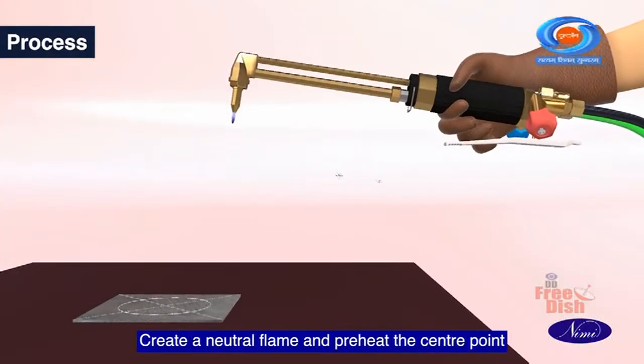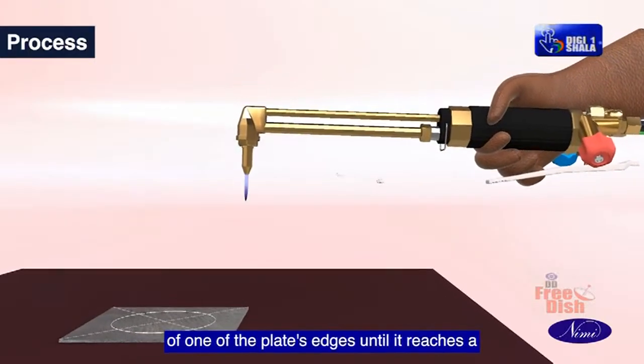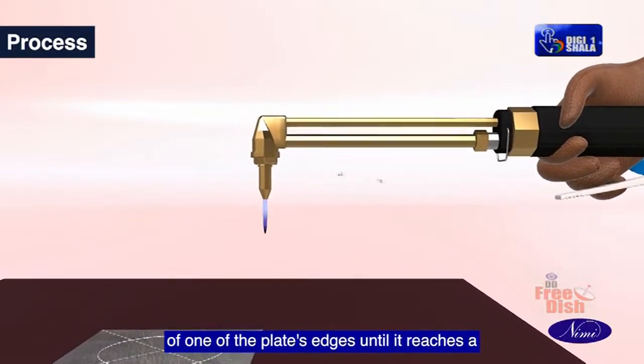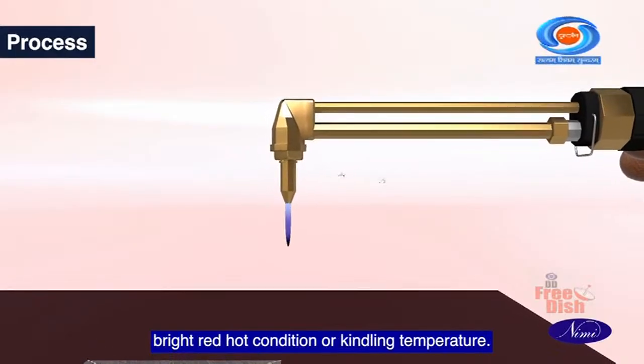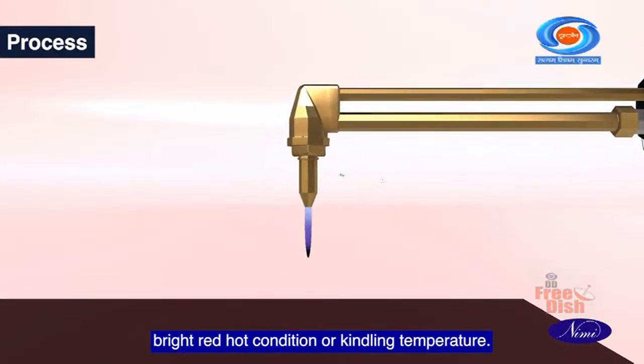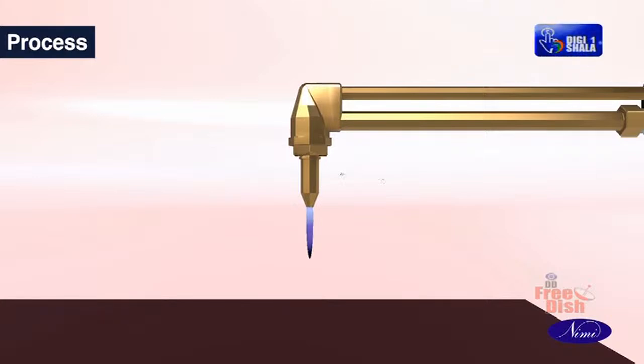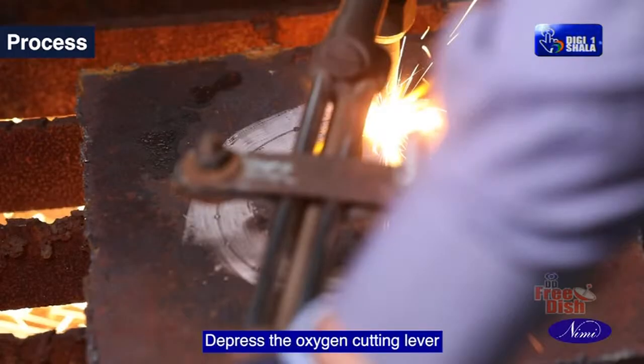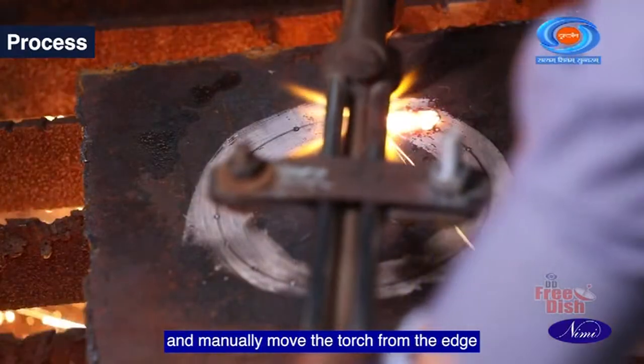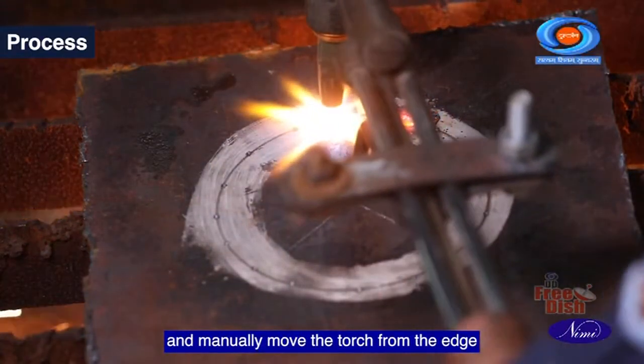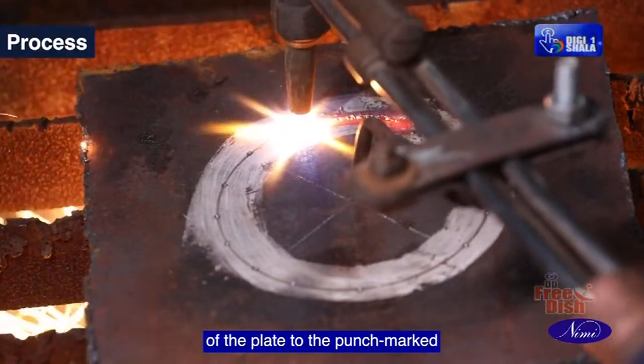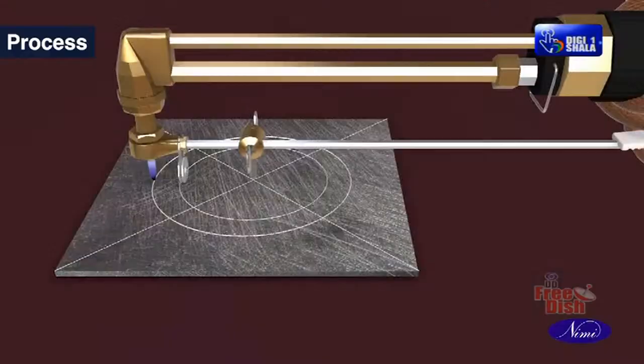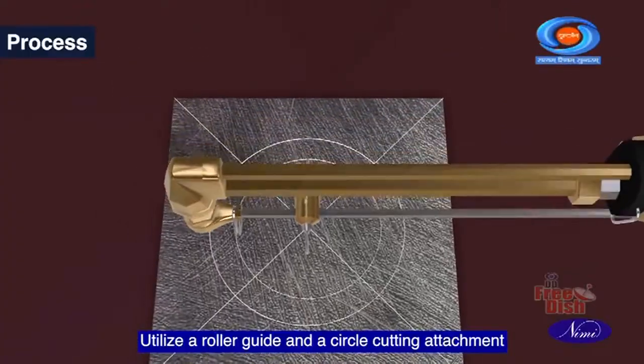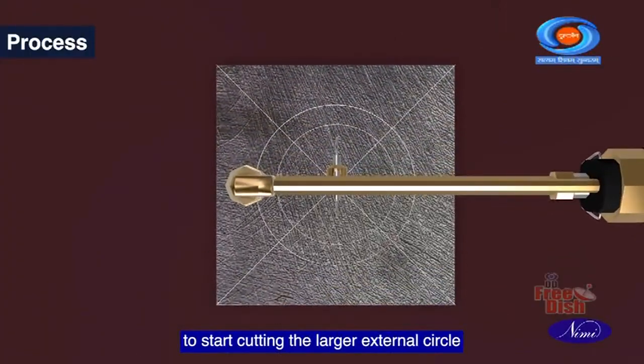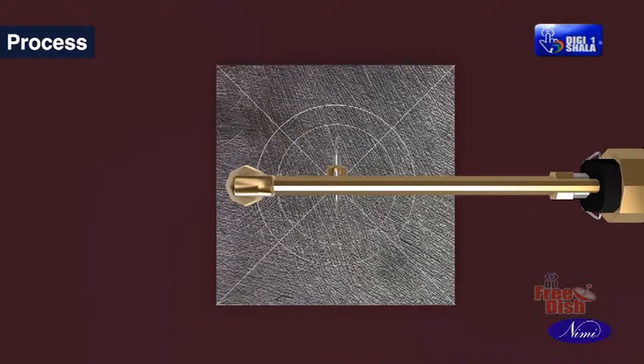Create a neutral flame and preheat the center point of one of the plate's edges until it reaches a bright red hot condition or kindling temperature. Depress the oxygen cutting lever and manually move the torch from the edge of the plate to the punch-marked circumference of the larger circle. Utilize a roller guide and a circle cutting attachment to start cutting the larger external circle with a 90 mm diameter.